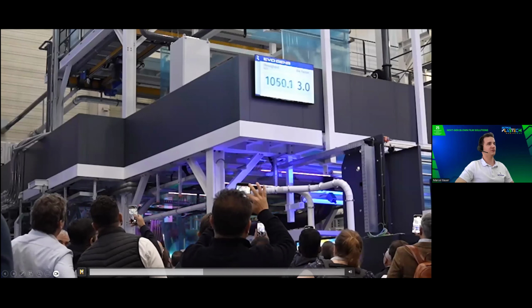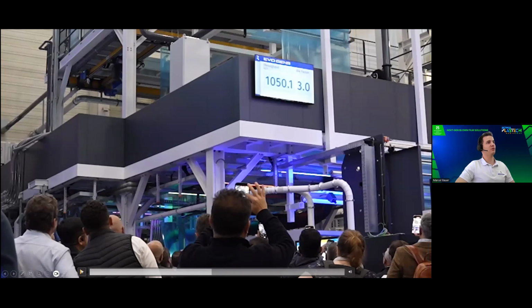So on the Evo Gen 3 here, you see we did run over 1,050 kilograms an hour with a die factor of 3. That means we run there with a die head, die insert of 350 millimeter and a lay flat of 1.8, running collation shrink and die factor of 3. So with a small die head, you can get this high output, is very enormous value, because then also your carbon footprint looks much, much better and the energy consumption is also very low.